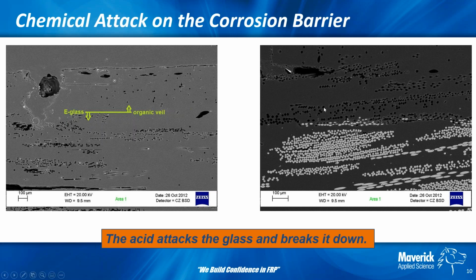So this is e-glass, so you can see that the sulfuric acid has attacked it. It's leached out the elements, and it leaves these conduits behind where the glass was. Though you can see the white circles here are where the e-glass is still intact. And you can see these oblong ovals here. So this is actually your woven roving layer. You can see where your chop is coming down here, and then where you start to hit, this is probably your first couple mats in your structure, and then you're seeing your alternating woven and mat going forward there.